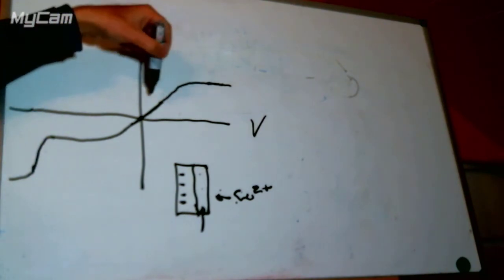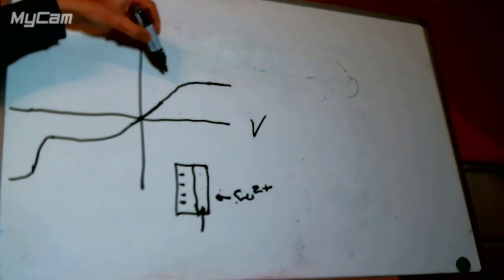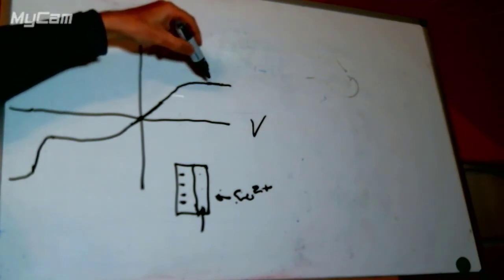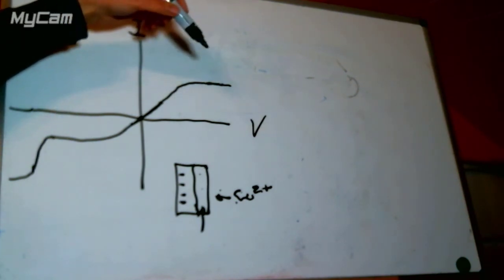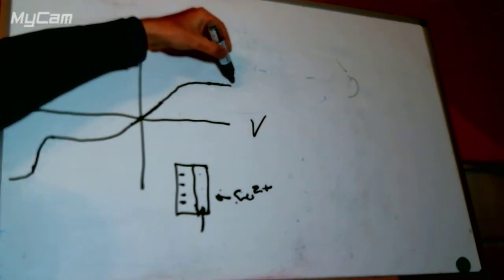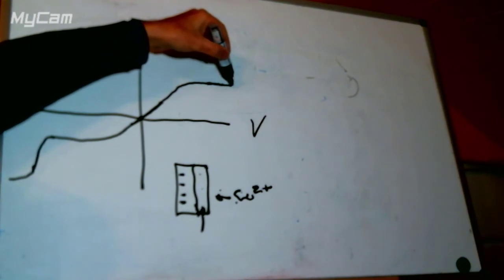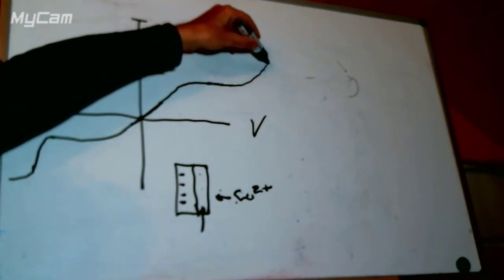If we go this direction, we are dissolving it. So we're stealing electrons from the solution, we're discharging copper ions, but eventually we'll start to discharge water, and we will get, so we're removing electrons from it, so we will be, what are we doing? Yes, we're removing electrons from it, so we'll be making protons from water, and so our current will also go up.